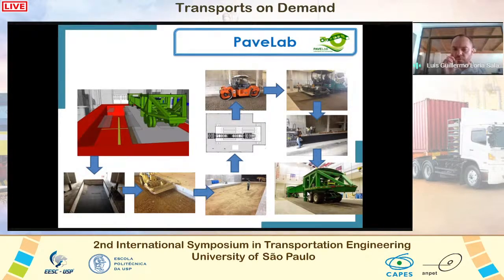If you talk to your technical engineers, they don't like it if you treat the subgrade like that. But in a very rainy country like Costa Rica, where the water level is very high, if you don't seal your test pit very well, the natural water level is going to mess up your experiment because it's going to produce uncontrolled fluctuations. We didn't want that. We placed the subgrade, and on top of that we put the granular base or subbase, the cement-treated base, and the hot mix asphalt layer.